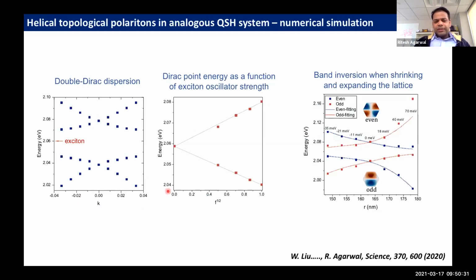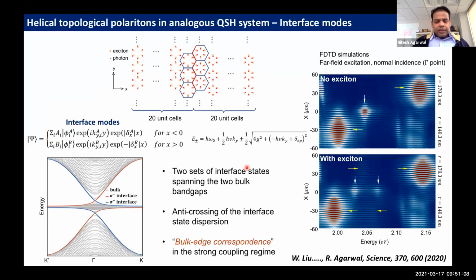These are more calculations to show that as a function of these lattice parameters, one can invert the system. If the valence band has odd parity, as in a regular system, then by changing the lattice parameters, these calculations show that indeed we can invert, and in this regime the valence band can have d-type orbital characteristics in the polaritonic regime. This is not the photonic regime. Now, when we create an interface between the two polaritonic lattices, so this is the interface, we solve the interface mode equation.